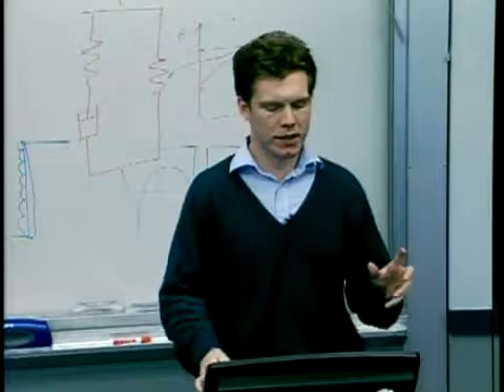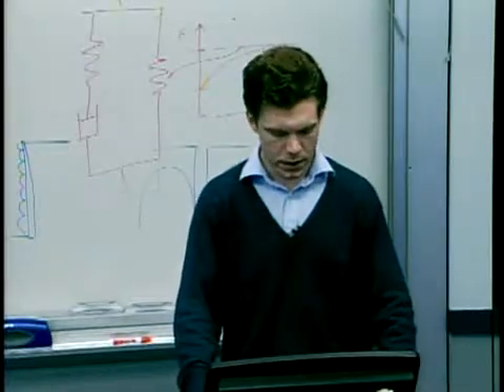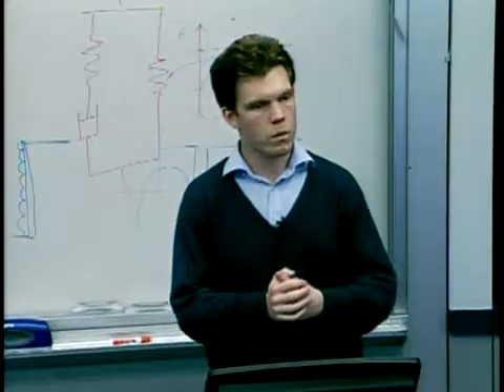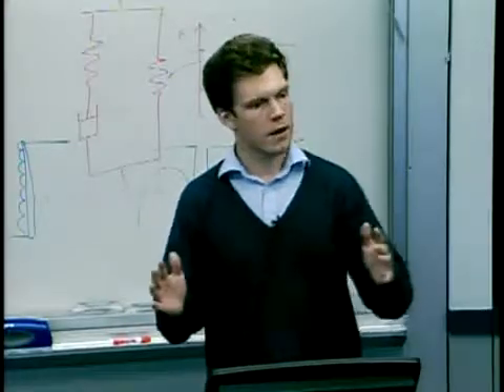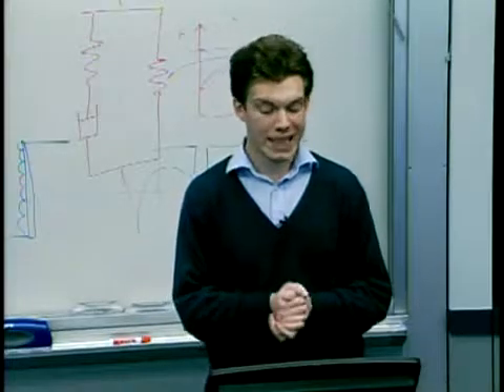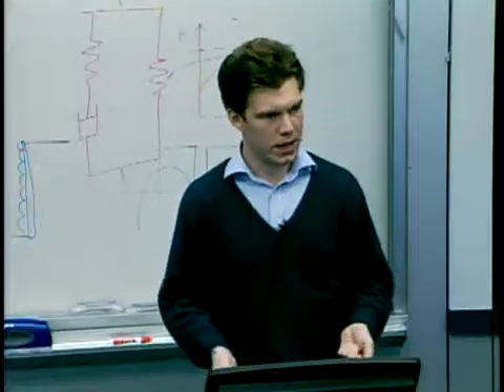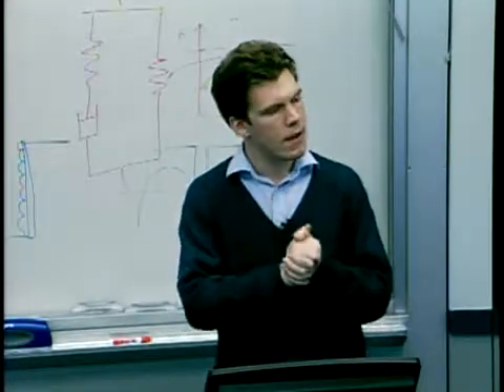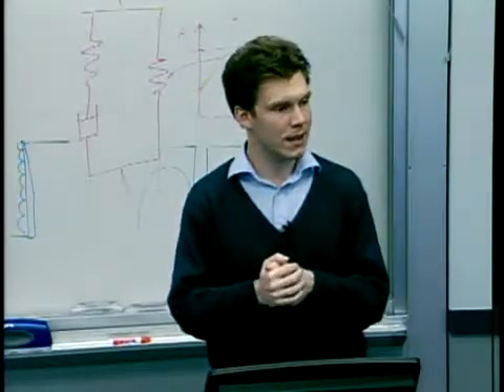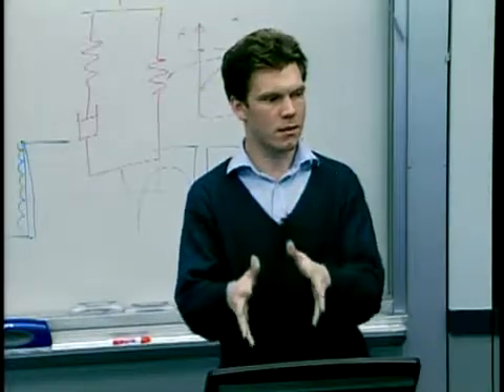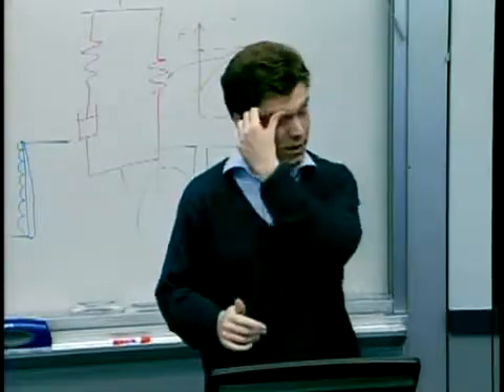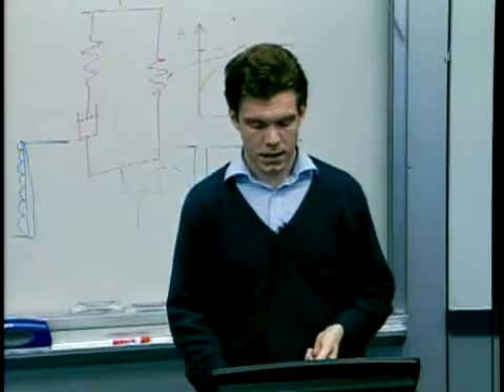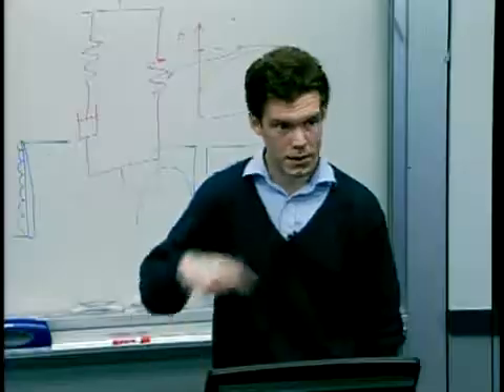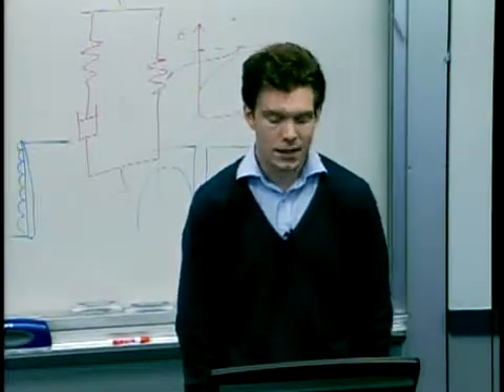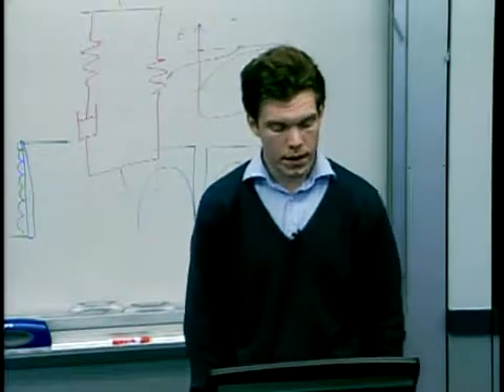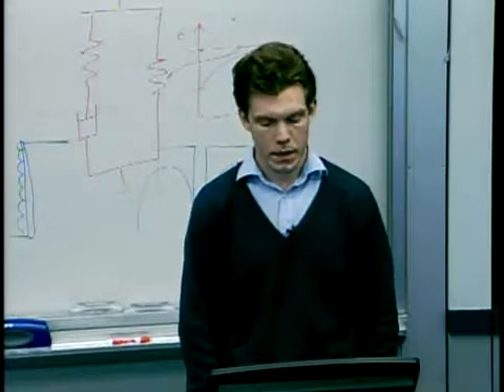Anyway, the point of saying all this is, as I alluded to a few minutes ago, you might think of reducing the temperature swing to as small a value as you can, so that the amount of thermal contraction is restricted. You might even think of removing the load slightly above the glass transition temperature. If you're in a region where some of the deformation, or most of the deformation, is actually plastic, which is true in a region about 10 degrees above glass transition for PMMA, and you can exploit the material properties to avoid having a big temperature swing, then that could potentially be very exciting. Together with Matt Dirks, who's in the Lab for Manufacturing and Productivity, we looked into this a couple of years ago, and found that if we control the temperature really carefully, then it was promising.